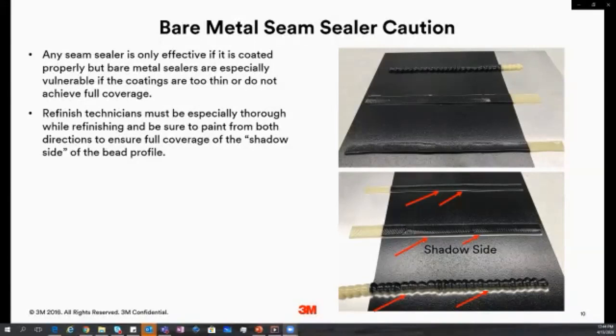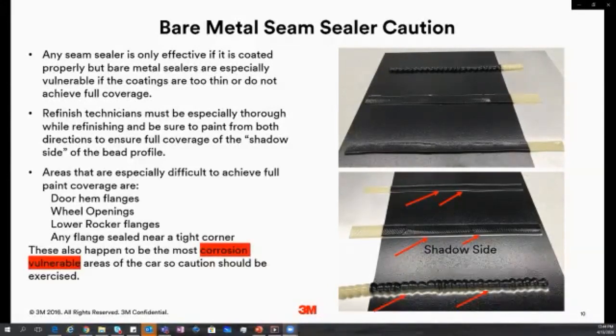And the corrosion will build on the surface of the panel, and it'll work its way underneath the seam sealer. It happens with panel bonds. It happens with seam sealers. It bites into the surface of the metal, and it just eats away, inevitably causing a failure. And a lot of the areas that we see this are very vulnerable to corrosion, right? Areas like door hem flanges, rocker panels, and wheel opening areas, where we have to be putting a seam sealer bead, because from the factory they may have had it and we need to duplicate that. Or maybe they're suggesting that we put one there to make it more resistant to stone chips and so forth and corrosion.